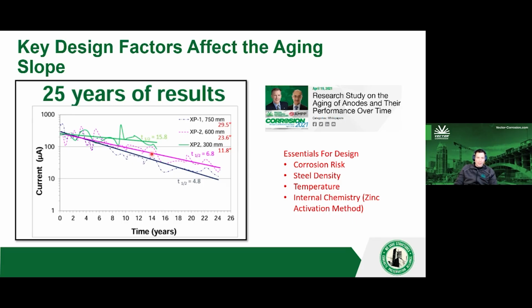These three degradation curves, aging slope curves on the current dropping, are on the same structure, using the same types of anodes, just at different spacings, different things going on. And I want to show you this to tell you that we know which knobs to turn to make this aging curve either very flat or very steep. We know what changes that slope.